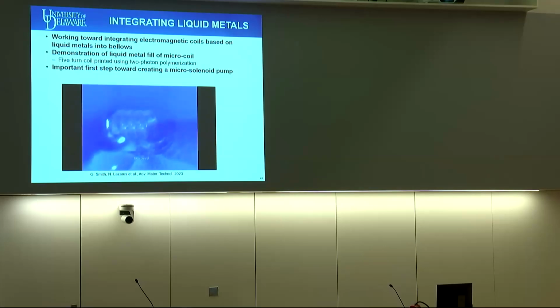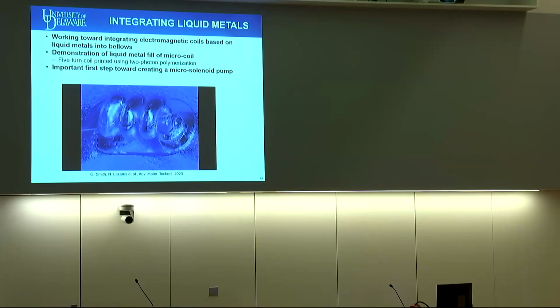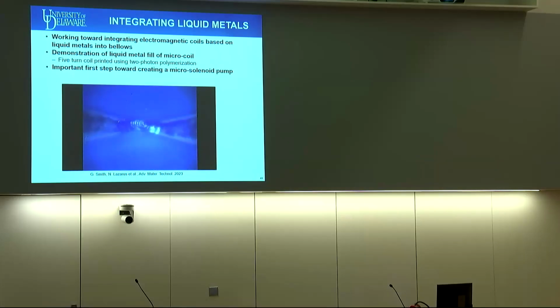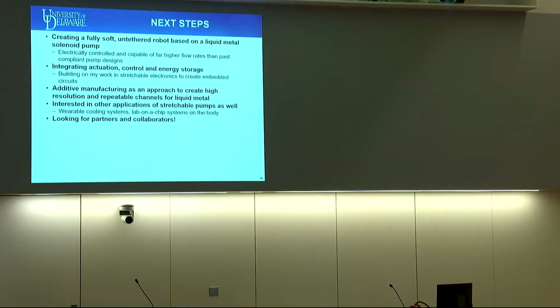More recently, we've been looking at combining this approach with adding liquid metal into something like the bellows. So we can use electromagnetic actuation to replace the needle probe and have a more self-actuated structure. This shows a 5 and a 3 turn coil using 2-photon polymerization that we're then injecting liquid metal into to create our final inductor coil. So in conclusion, we're really looking toward building on this work to make a fully soft untethered robot based on a liquid metal solenoid pump. We're trying to get electrically controlled and significantly higher flow rates than past compliant pumps, and to leverage some of the work I've done in structural electronics to integrate actuation, control, and energy storage.